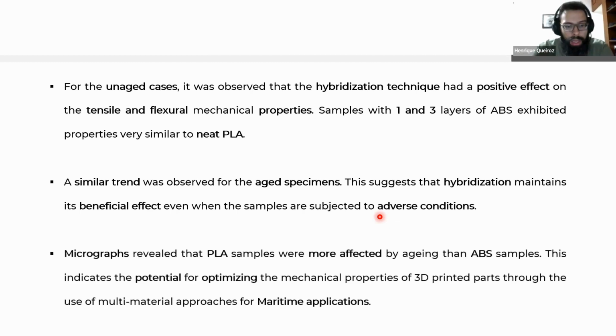And the micrographs also revealed that, as expected, the PLA was more affected than the ABS, but we also saw how it was more affected. It had more localized debonding than the ABS did. And so there is room for general optimization there.